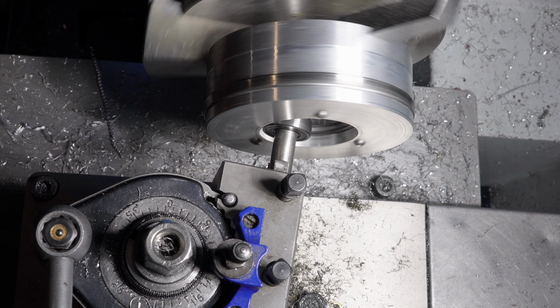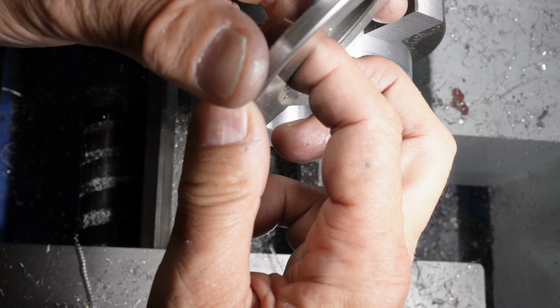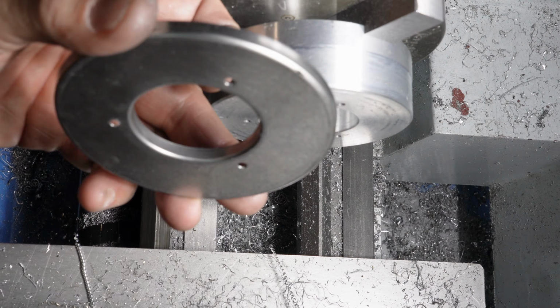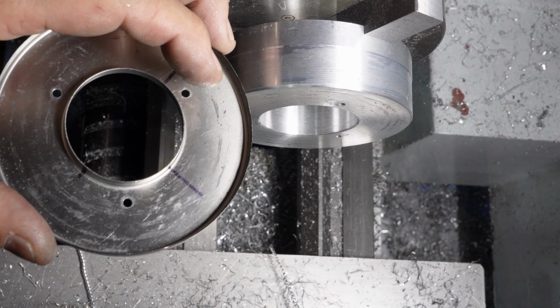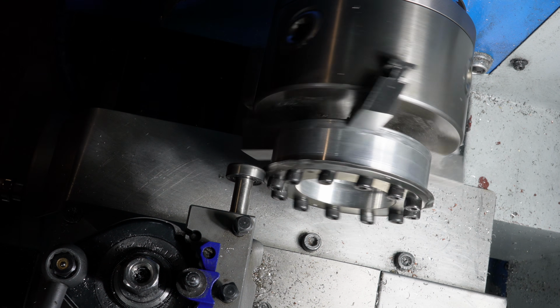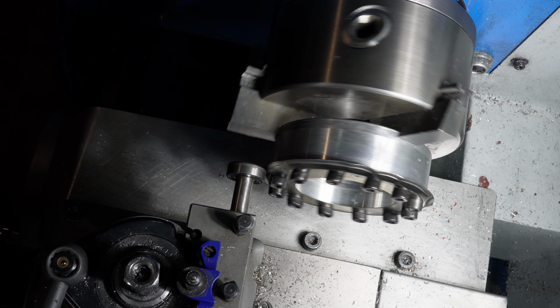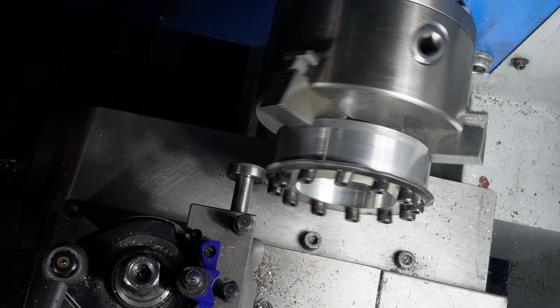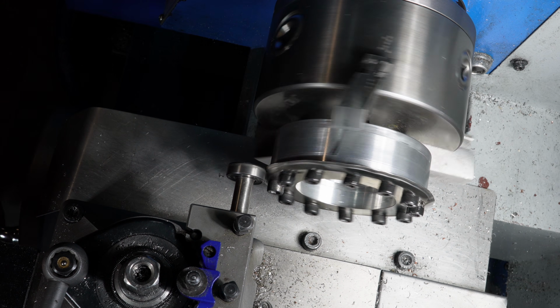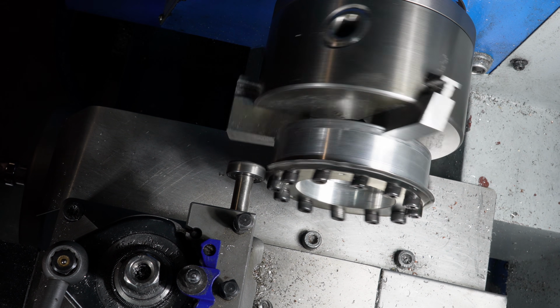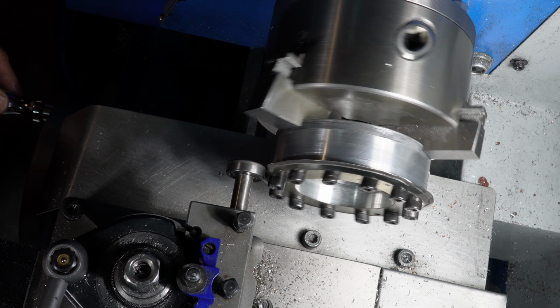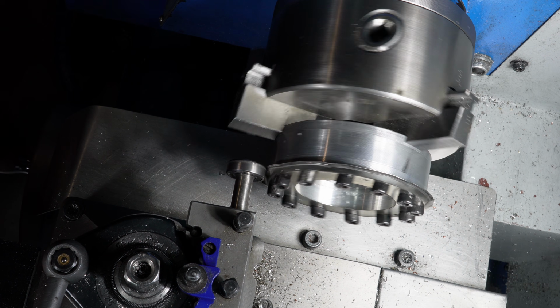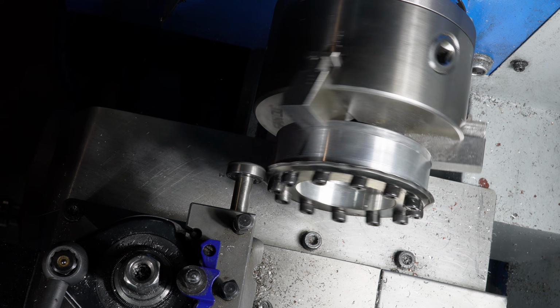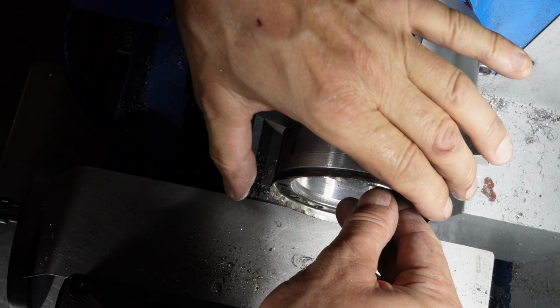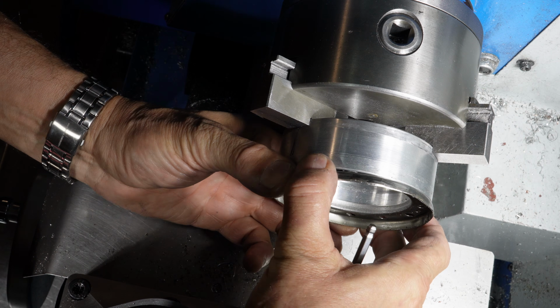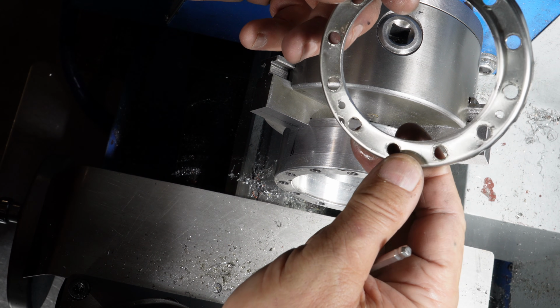Although the process works reasonably well, achieving perfectly repeatable results proves more difficult than expected. Sometimes the parts come out exactly as planned, but occasionally wrinkles appear at the edge and the part becomes unusable. Another challenge is controlling the final dimensions, because the flange rarely ends up at exactly 90 degrees. After several attempts, I decide to change my approach. Instead of forming the end caps from sheet metal, I machine them directly from solid stainless steel stock.